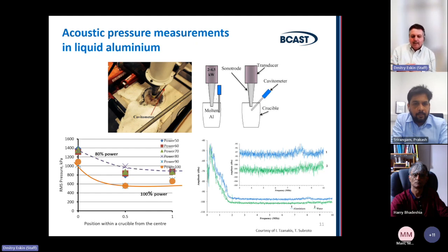It is an extreme case. But if you talk about aluminium alloys with different viscosities, you add some magnesium or silicon and iron, they change the viscosity of the liquid metal. So viscosity affects the dynamics. If you have lower viscosity, you have better accelerated processes. So for degassing, the bubbles will rise to the surface quicker. They also will be larger. If you have low surface tension, they will also become larger and absorb gas more efficiently.